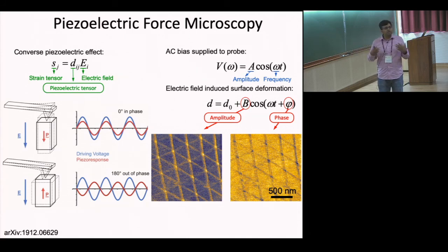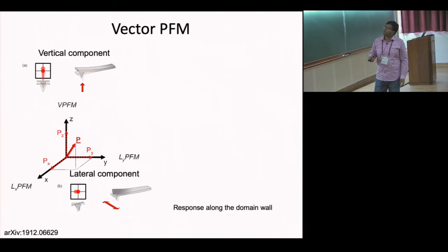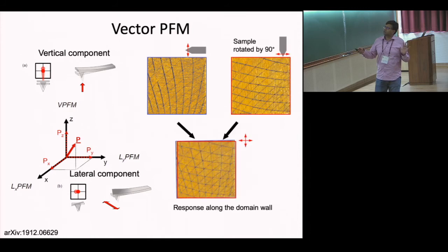We found that all of these Moiré patterns display a beautiful piezoelectric response when you probe them in this fashion. And we can go a little bit further. We can look carefully and see where the displacement of the sample is for a given electric field. I'll cut this story short. If you apply an out-of-plane electric field, the sample displaces along the domain wall. So it's an off-diagonal component of the piezoelectric tensor that's responsible.